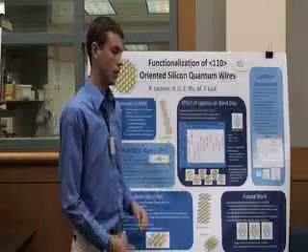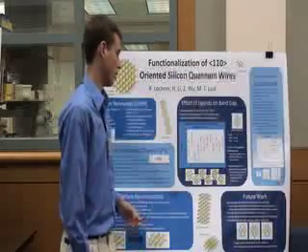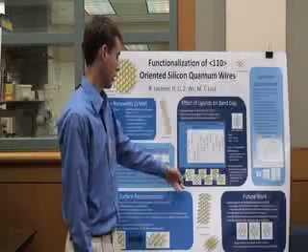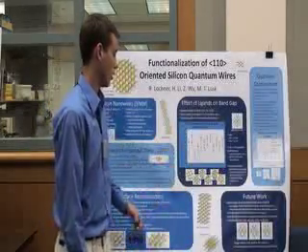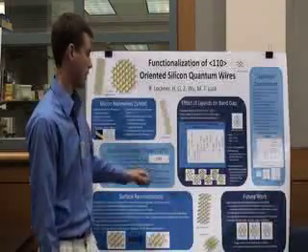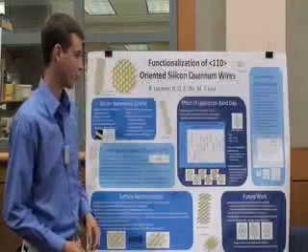And so the results we noted were similar trends for wires and dots, and also a highly tunable nature of the HOMO-LUMO levels, because as you can see here, fluorine drops the HOMO-LUMO levels significantly. And while these results are not necessarily good quantitative predictions, they are good qualitative predictions, and so that's something interesting to know.